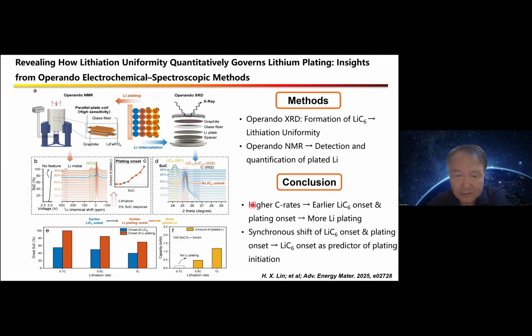We found from the XRD patterns that at higher C rate, the earlier lithium carbon-6 onset happens.